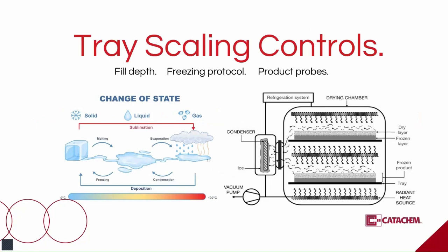When scaling to trays, three practical controls dominate. First, control fill depth. Shallow fills freeze and dry more evenly. Deeper fills increase resistance and create a higher probability of incomplete drying and local temperature gradients. Second, match the freezing protocol to scale. A controlled shelf freeze at bulk scale helps prevent non-uniform crystal formation. In trays, non-uniform ice can create non-uniform pore structures that then translate into non-uniform drying.